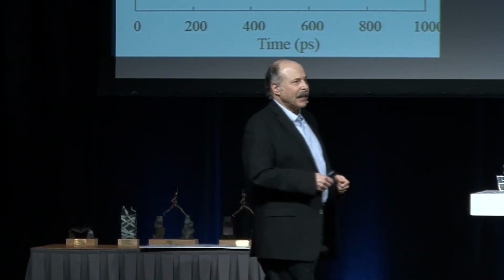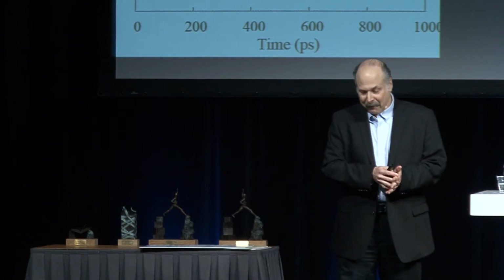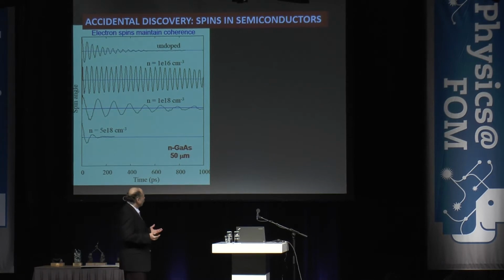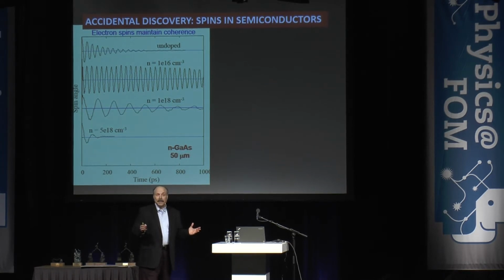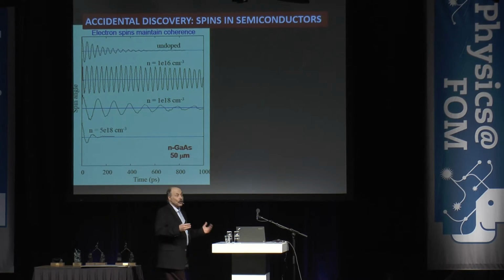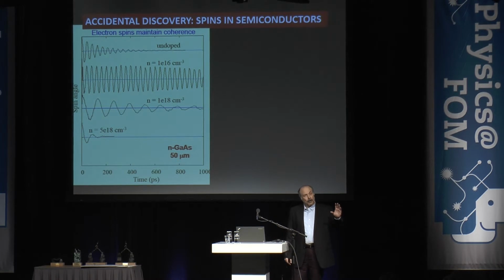Yes. Gallium arsenide has always been referred to as the material of the future. So these were experiments to put magnetic ions into gallium arsenide, and then there was a simple control measurement to take out the magnetic ions, look at commercial wafers just purchased online of gallium arsenide, illuminate these wafers with a polarized pulse of light above the band gap of the semiconductor, so that generates spin polarized electrons, put a perpendicular magnetic field, and just watch them precess. Look at how long these puddles of coherent states should last. And it was expected they wouldn't last long at all.